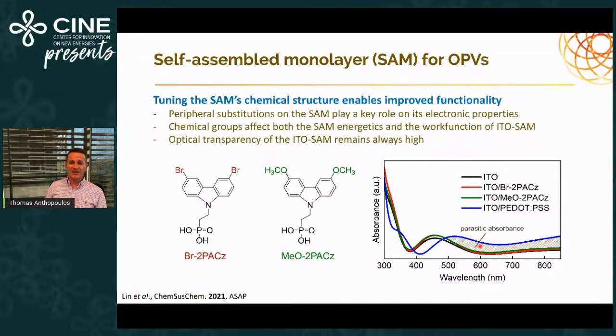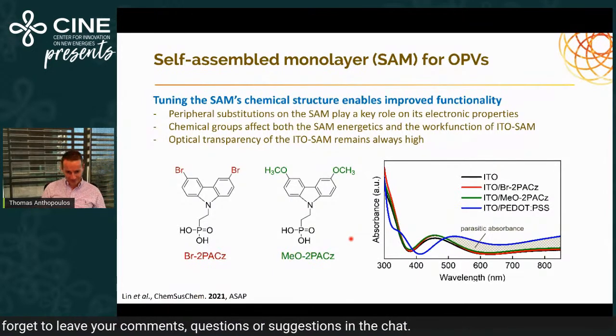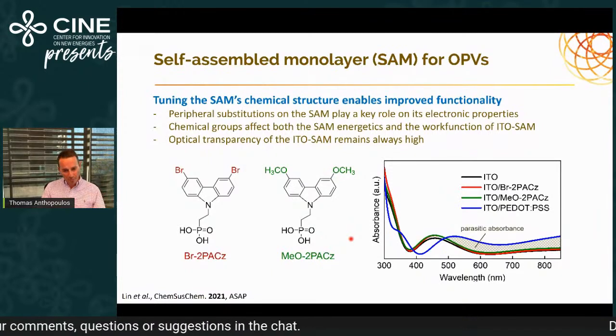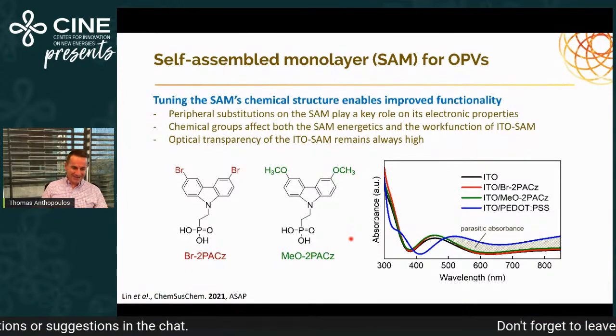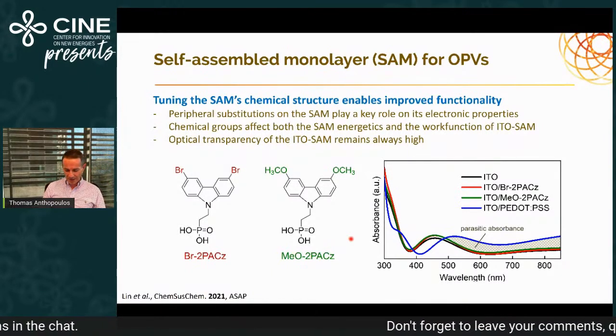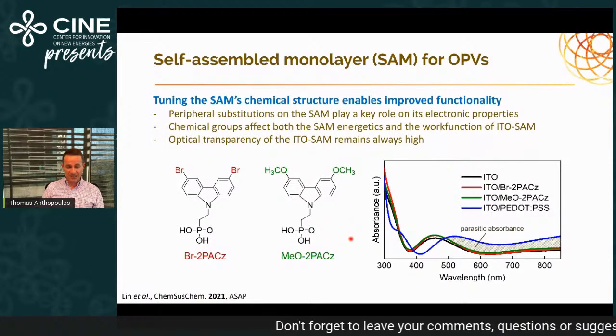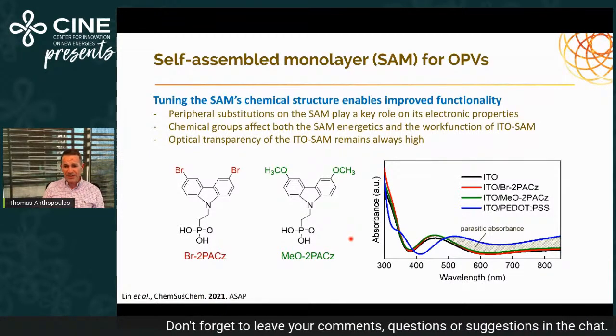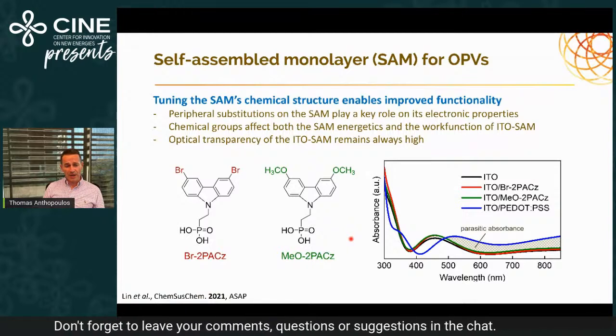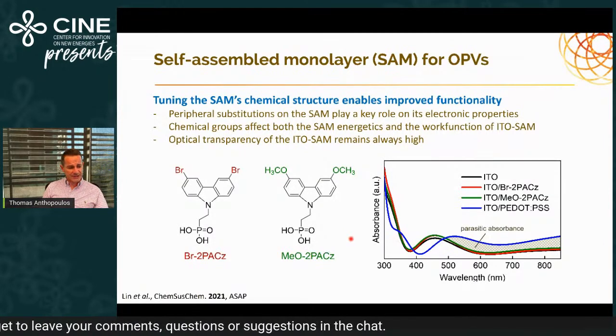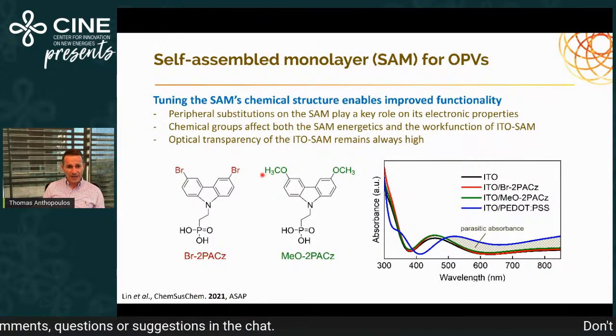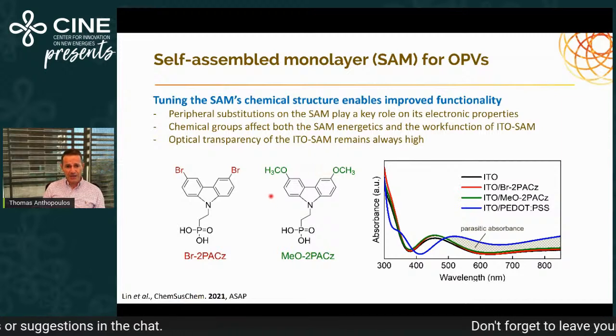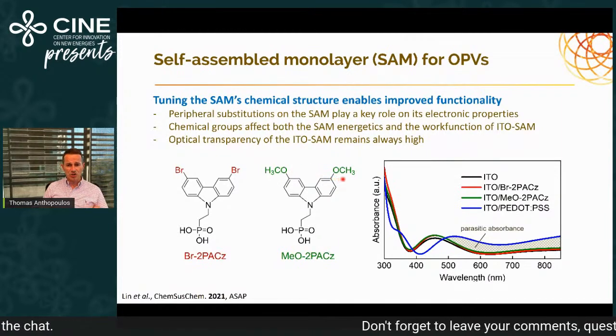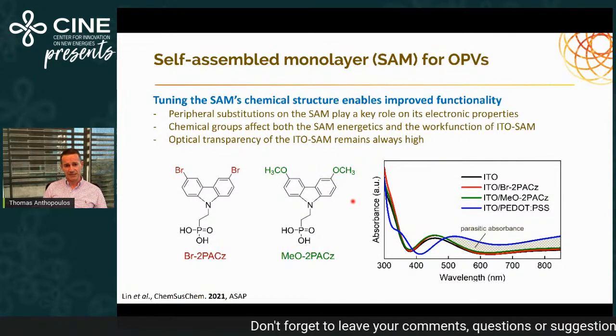Of course, removing this parasitic absorption doesn't automatically mean we gain, because it all comes down to how we photonically structure a device. We can play with other parameters to compensate for that parasitic absorption, and this is what we often do for PEDOT:PSS-based solar cells. But nevertheless, it shows that we are now dealing with monolayer systems where we can start tuning the periphery of the molecule atom by atom and make a huge impact on the performance of the devices.